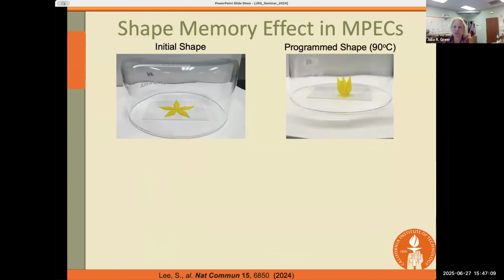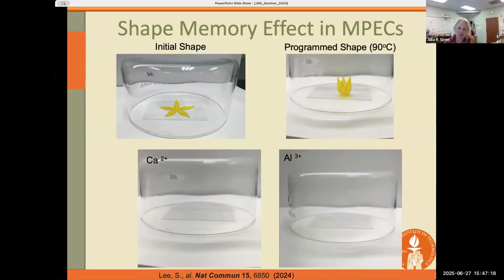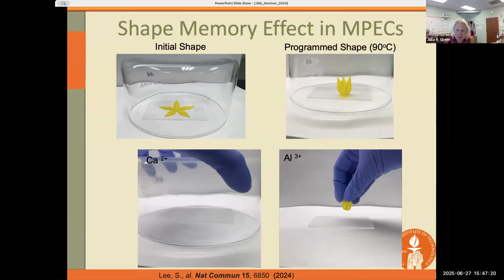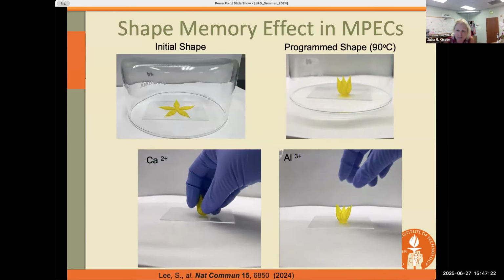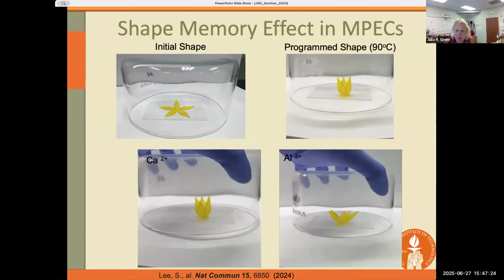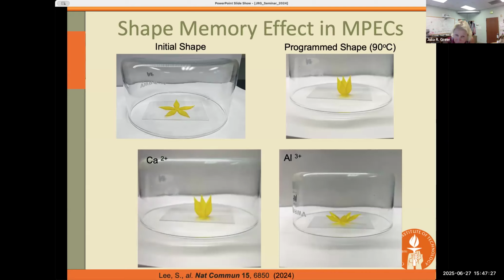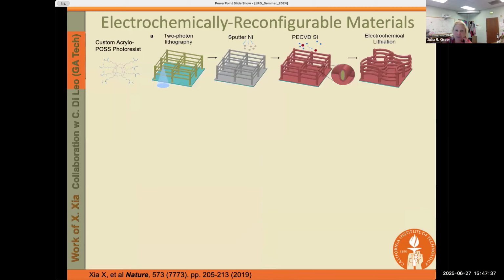And this is just to show you that if we program the shape, for example, a blooming flower, here's the calcium versus aluminum comparison. We place them down into the pre-programmed shape, and you can see that they're both blooming back to the initial shape, but the rate at which they're blooming is very different between the two. So you can start thinking about how you can make actuators and active materials using this approach.